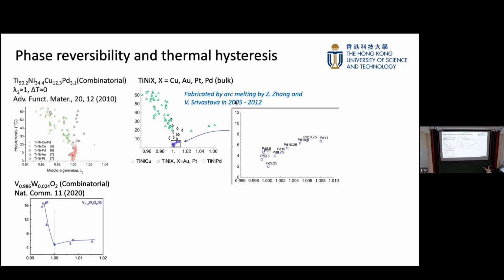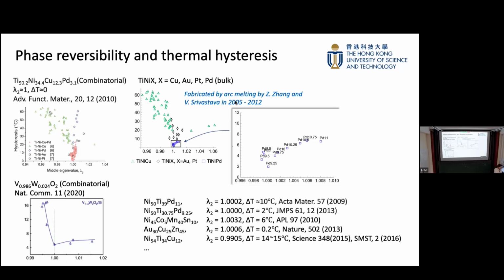And if we blow up the bottom here, we find that with an even finer tuning, I think the published result probably is here at palladium 11. I think Dick already showed that many, many times. And then we made very, very fine tuning. I just slightly change the composition, and we find that it can minimize here, even closer to lambda 2 equal to 1. We also have many other phase transforming materials, some Heusler alloys. This is a ferromagnetic shape memory alloy. And we have some single crystals, this is a single crystal, and other examples are polycrystalline. What I want to show here is that the minimal hysteresis is different in each material system.